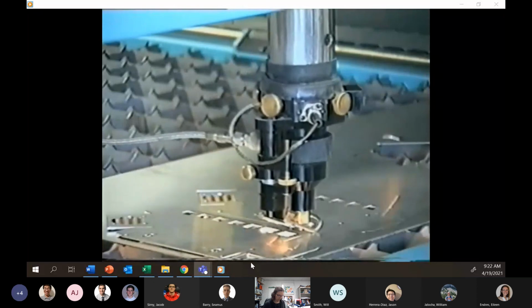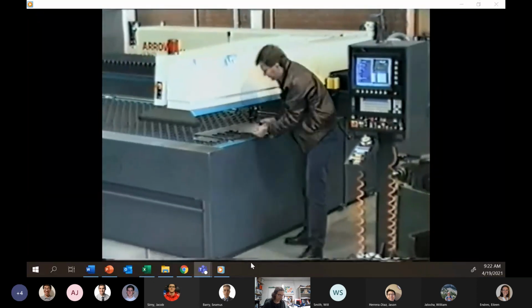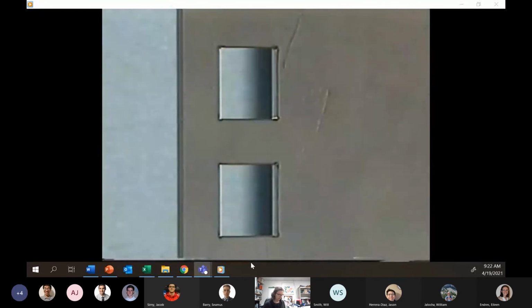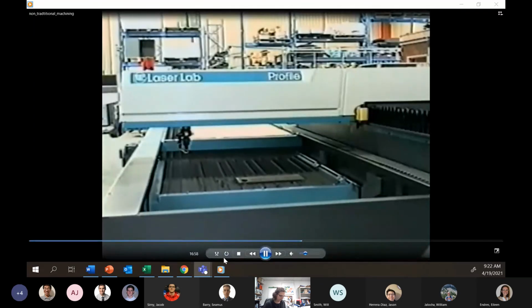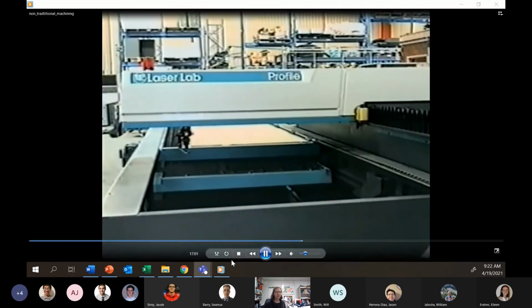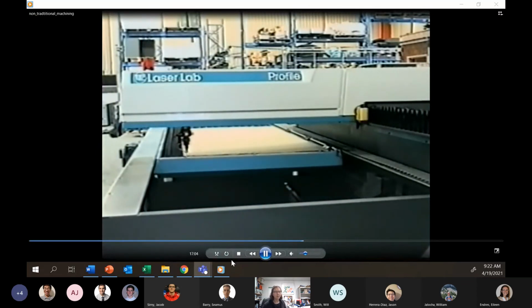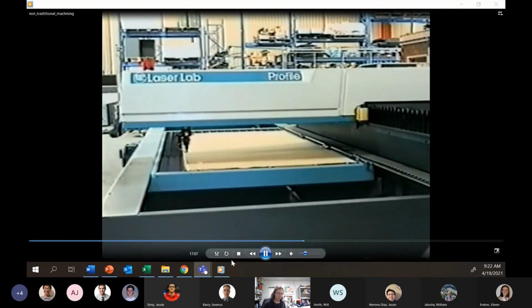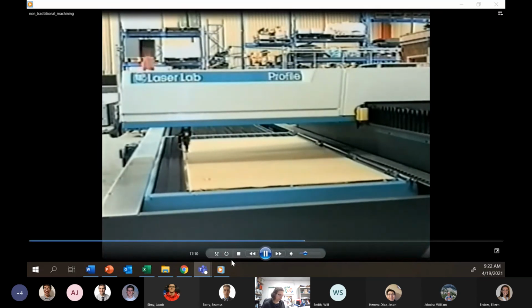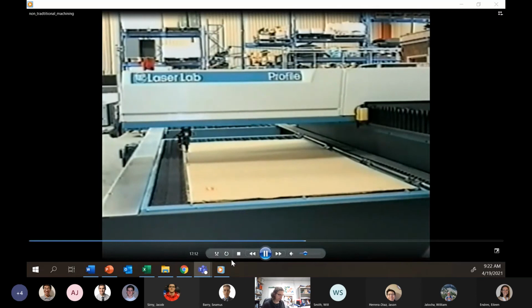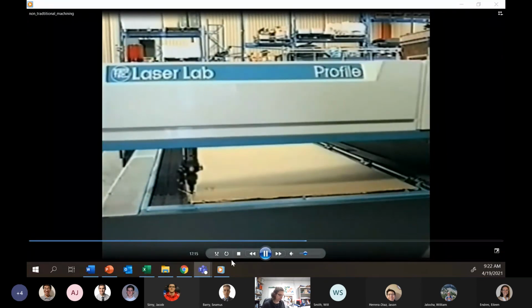The cut width is less than 0.2 of a millimeter. The complete shape is cut out in 1 minute 38 seconds. The edges are clean, square and smooth. This process is ideal for medium-sized production runs where the cost of a die set would be prohibitive. It is also perfectly suited for just-in-time requirements, where small batch sizes are required, as changes from one material to another can be accomplished within 1 to 2 minutes.